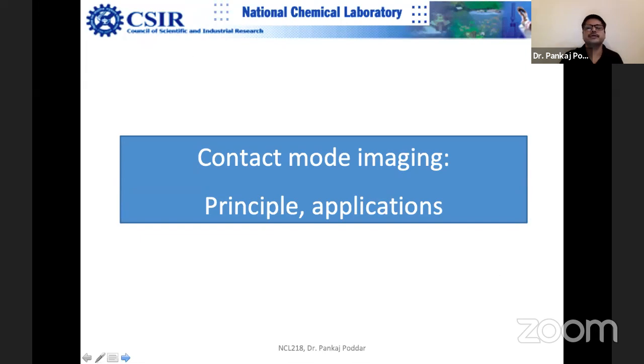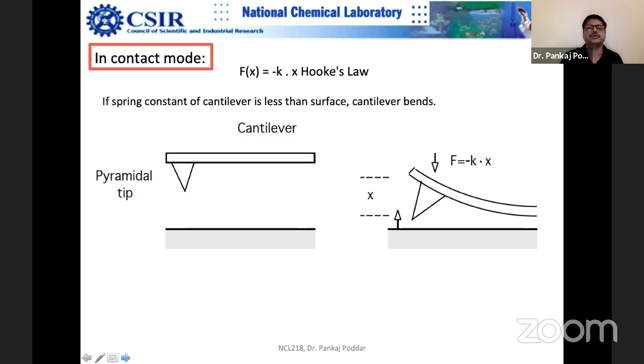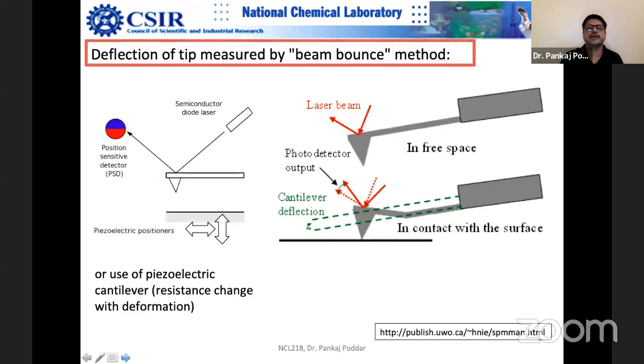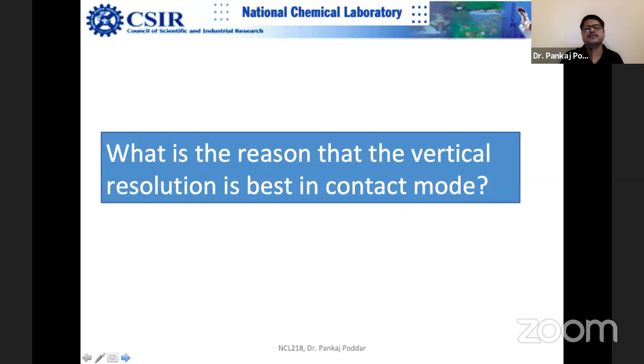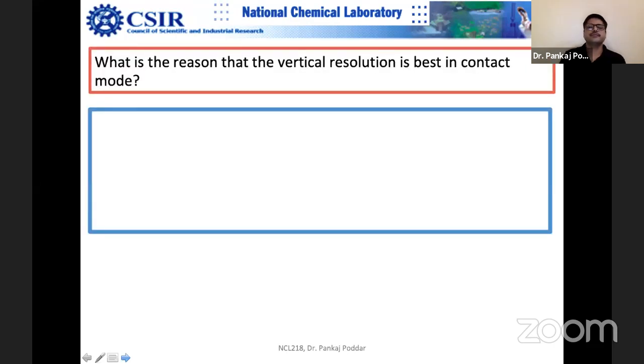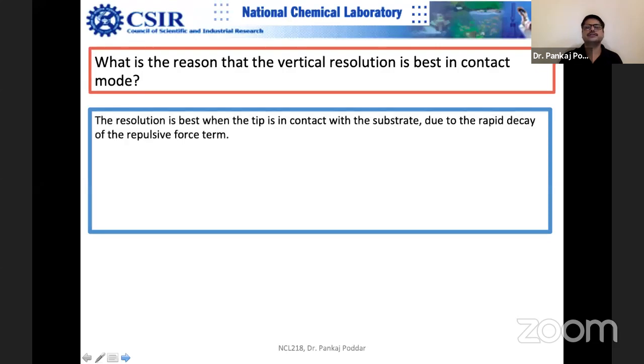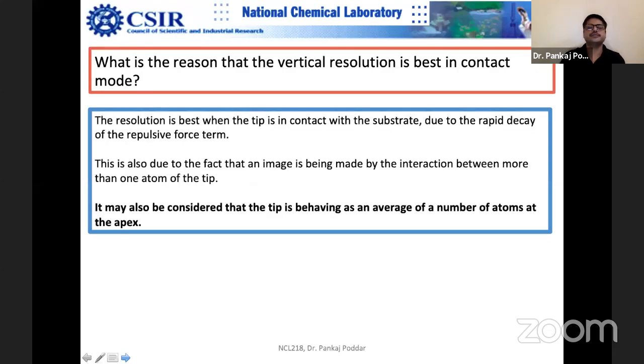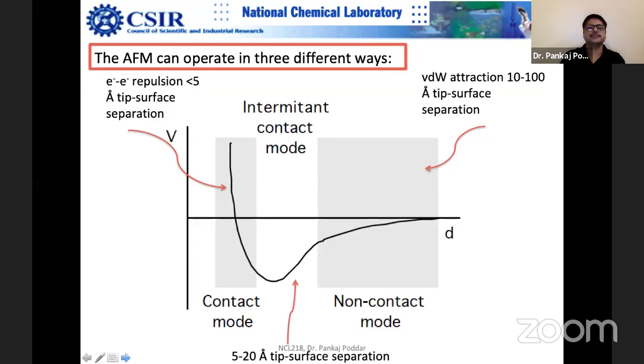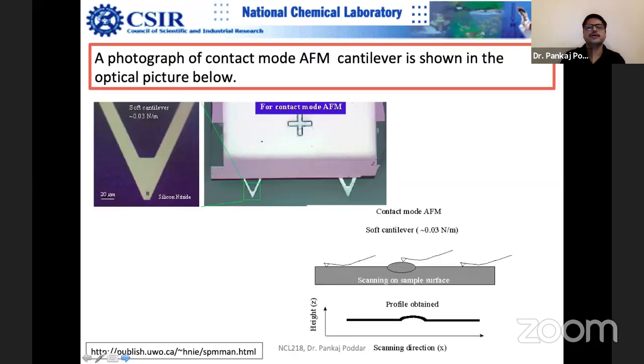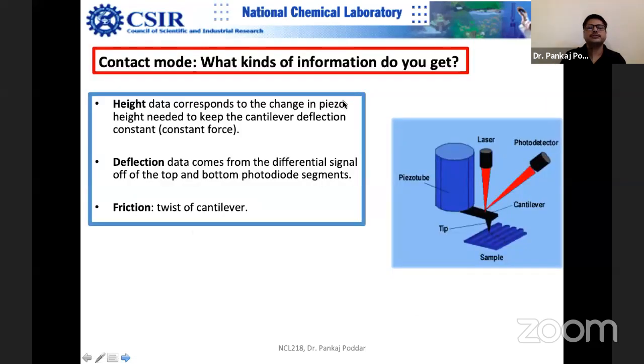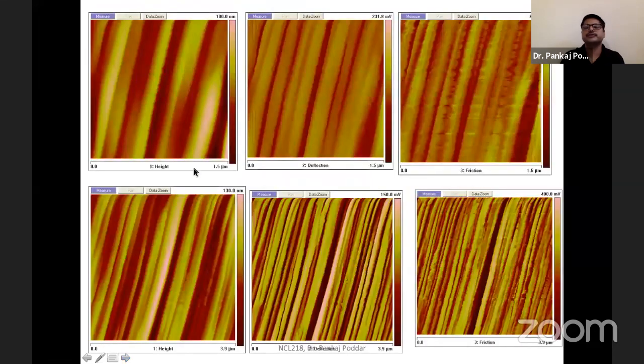And then we moved to contact mode imaging. We mentioned two modes, constant force mode and constant height mode. Constant force is basically where you try to keep the deflection constant. But if you are not able to do that for rough samples, you tend to get error measurements, and that is not very useful. So these are the three information you get in the constant force mode: height, deflection and friction. So this is frictional force microscopy, deflection is the roughness, and this is the height of the sample.